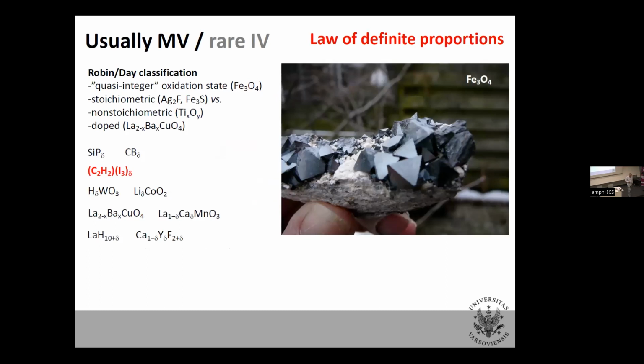However, there are compounds that pretend to have non-integer oxidation states of elements. So if you take FeO, that's iron 2. If you take Fe2O3, it's iron 3. But this very, very old known Fe3O4 seems to have a peculiar oxidation state of iron of 8/3+, which is non-integer, of course. And the truth about this compound is, in fact, it has both iron 2 and 3 in a certain proportion. So if you just look at the formula, it's fooling you. It's a mixture of known oxidation states.